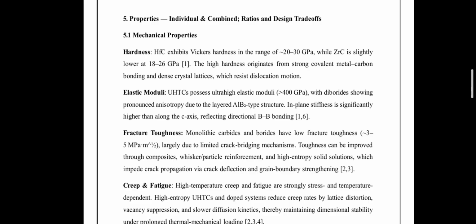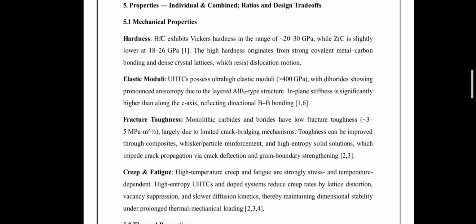Next is fracture toughness. Despite their strength, monolithic carbides and borides suffer from low fracture toughness, typically ranging from 3 to 5. This brittleness arises from limited plasticity and the absence of effective crack bridging mechanisms. Toughness can be enhanced by composite architectures, such as particle reinforcement and high entropy solid solutions. This approach impedes crack propagation through crack deflection, grain boundary strengthening, and stress redistribution.